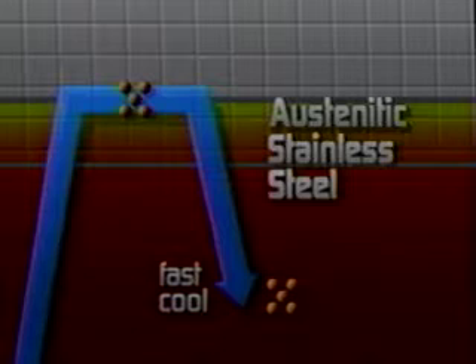For instance, when the austenitic stainless steel is stamped to make a sink or cold rolled during processing, it is work hardened and must be softened again by heating and quenching. And here's what's unique about quenching austenitic stainless steels. They must be quenched rapidly, otherwise they become susceptible to corrosion. Stainless steels are corrosion resistant because they contain chromium.